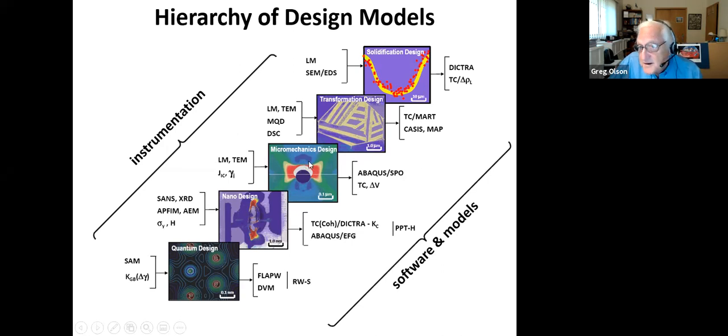Equally important is the constraint for scale-dependent processability of materials, and that's enabled by the materials science models of solid-solid and liquid-solid phase transformations, which are scale-dependent through heat transfer. And taking that into account, using macroscopic process models for the final scale of production of material, it's been possible to constrain a design upfront to be processable at the final scale of production. The software models and their platforms are represented by these acronyms. Equally important is the advanced instrumentation that has allowed us to calibrate and validate these models, and importantly, quantify the uncertainty of our model predictions to incorporate in our design practices.